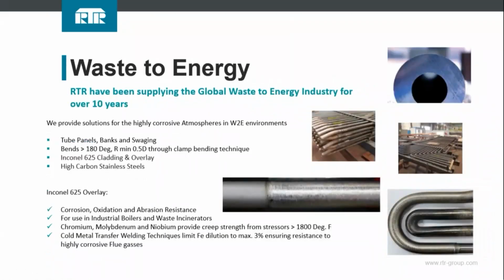As I said, we see waste to energy as a real growth. In the UK, for 10 years, we've been supplying waste to energy. It's gone from a handful of sites in the UK to more than 100. We're aware of 2 sites being built in Perth as well, or around Perth. And you can see the products that we offer in terms of the panels and tube banks, swaging. This is all carbon steel through to high alloy, and then we're getting involved, as I said, with the overlay, which has fantastic corrosion, oxidation and abrasion resistance. And again, you can see some examples here of some of the external cladding overlay that we've been offering.